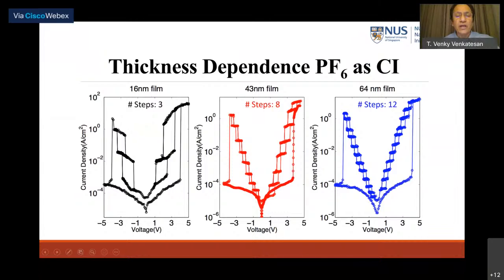Okay, let's take a 43 nanometer thick film. I get 8 hysteretic steps. Now, 43 divided by 8, again, is 5 plus or minus. Now, a 64 nanometer film, I get 12 steps. And if I divide 64 by 12, again, it is 5 plus some small change. So what is going on?